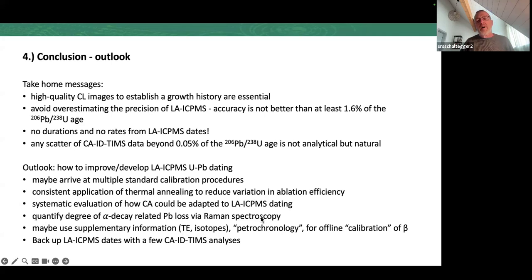We should use much more Raman spectroscopy to quantify the degree of alpha decay before we analyze the grains. The easiest is destruction-free. In most departments, there is such a Raman spectroscope standing around. And we should probably use supplementary information from trace elements. So what we call petrochronology, maybe we can use trace elements or trace element ratios to establish something like an offline calibration or an offline normalization, as we do for strontium isotopes, neodymium isotopes, where we do the fractionation correction online in the mass spec, but afterwards we calibrate externally for a systematic offset from standard.